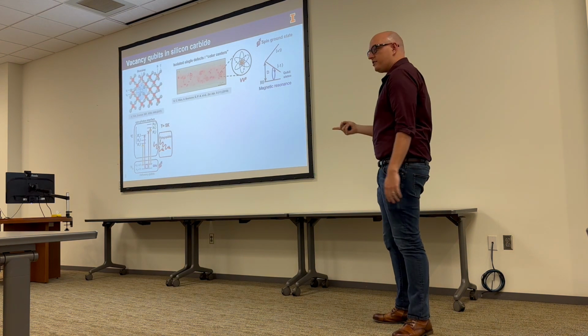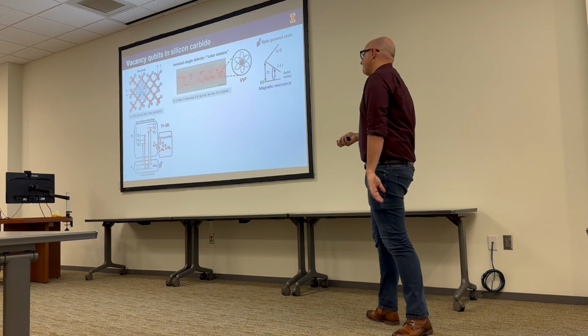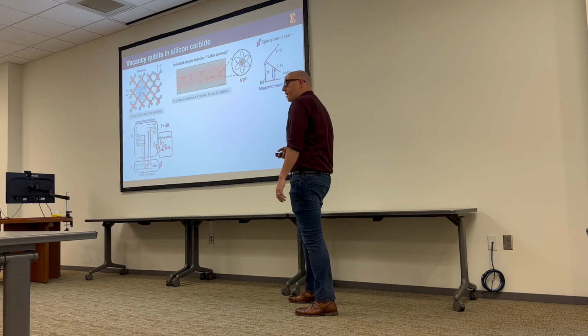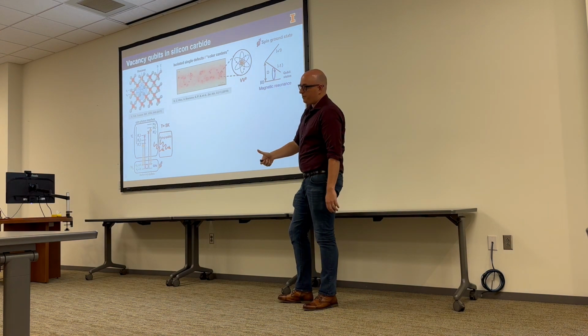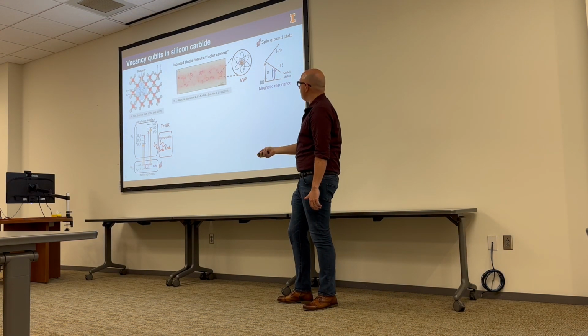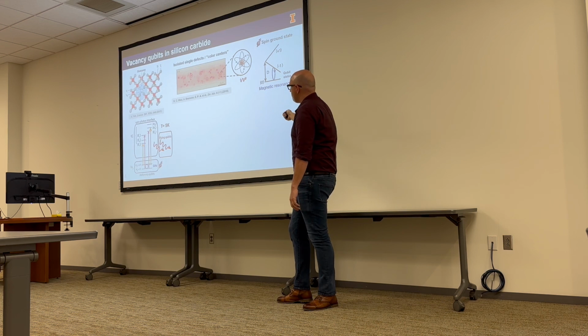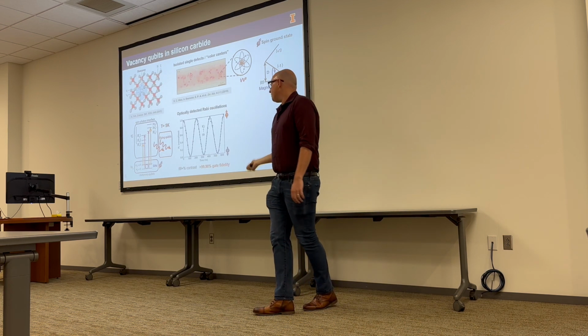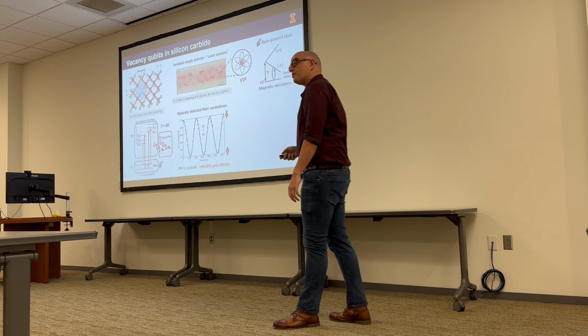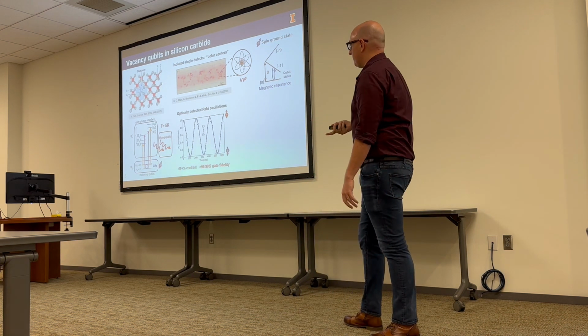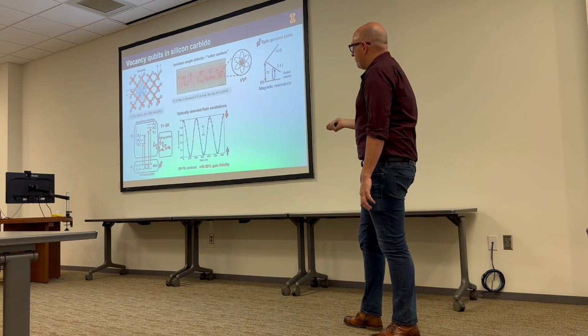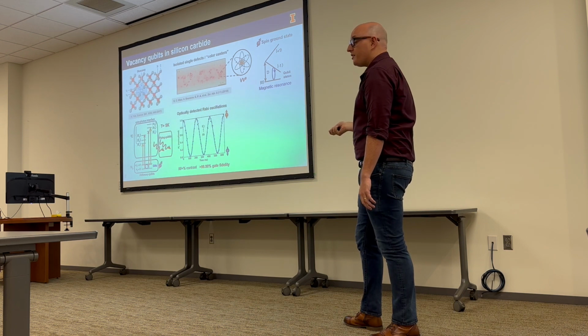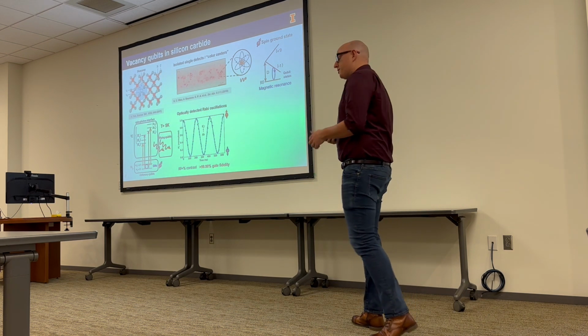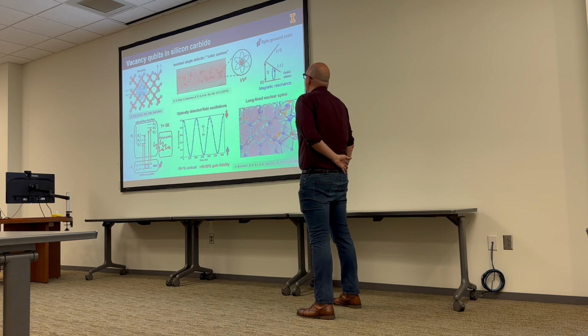So if we take a narrow line laser, we can do spin-dependent fluorescence, and we can play all the tricks from atomic physics to optically pump and optically read out our single spin. And if we combine that with this magnetic spin rotation, we can do optically detected rotations of a single electron in this solid. And I won't show you the details, but we can do this with extremely high contrast and gate fidelity. So we have very exquisite control of this quantum system.